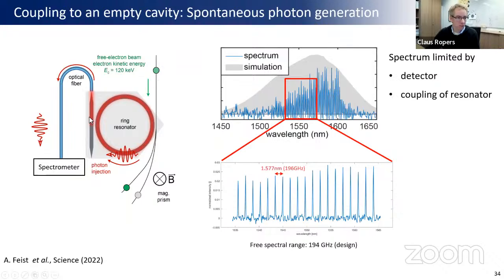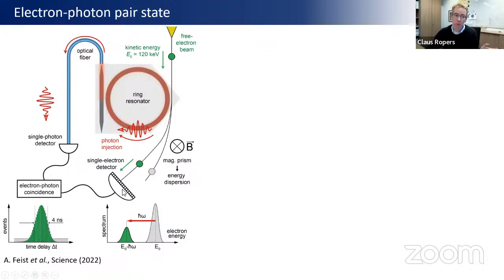Now, what's kind of interesting is what we can do here is not just measure the cathodoluminescence, but we also have the electrons which have passed by. And in the electron spectrometer, which is basically a magnetic sector spectrometer, they're deflected, and we can measure the kinetic energy distribution of each individual electron. Yeah, so this now allows, with a particular electron detector, which has single pulse timing resolution, pretty much, also for an additional signal.